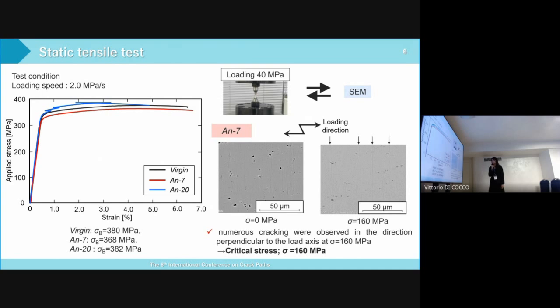at which cracking occurs. As shown in the upper right, the AN7 is subjected to a tensile stress of 40 megapascal, and then unloaded. And the surface properties of the anodized film are observed by SEM. This operation was performed once, and the loading and unloading tests were conducted by increasing the loading stress by 40 megapascal until cracking occurred. As a result, numerous cracks were observed in the direction perpendicular to the load axis at sigma equal to 160 megapascal. So it is defined as critical stress in this study.